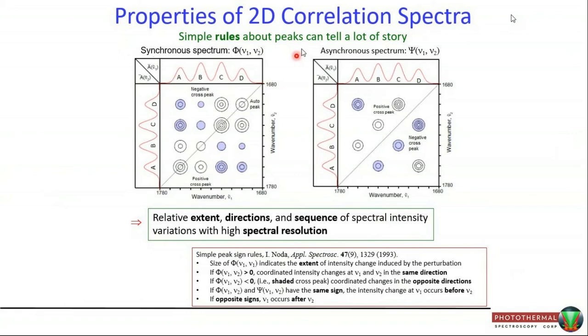Asynchronous spectrum will give you the sequential order of change. Now A and B actually are changing in slightly different sequence. If the cross peak signs are identical, the same positive, then horizontal band, band A, their intensity changes before the vertical band B. Likewise, if A and D cross peak signs are different, then horizontal band changes after the vertical band intensity. These are the properties that actually become very, very useful. So we're going to use this technique to analyze the spatially resolved spectrum.